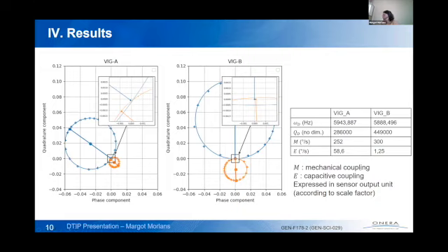So here are the results. We can see that first, these two cells did not have the same electronics associated. Indeed, here we see that VIG A had a phase shift of around 45 degrees, meaning that the cutoff frequency was close to the resonance frequency. However, the angle for VIG B was near zero.